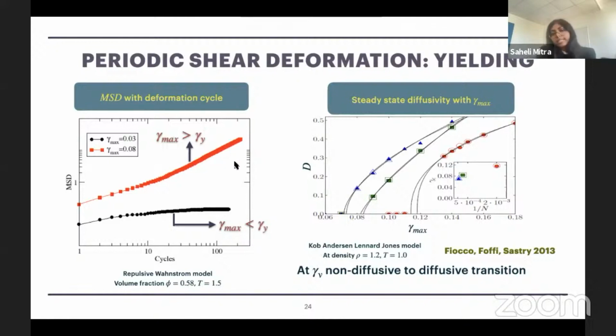Whereas above yielding, the mean square displacement keeps increasing and we have a diffusive state, and we can extract the diffusivity constant. So if we plot the diffusivity constant as a function of shear amplitude, we'll see below yielding the diffusivity constant is 0 and above yielding we have a finite diffusivity. So the yielding amplitude marks a transition from a non-diffusive to a diffusive state in the system.